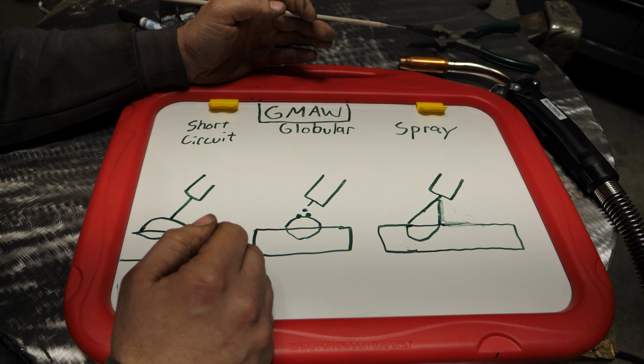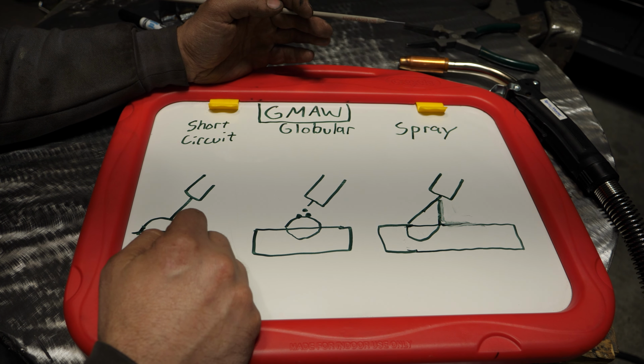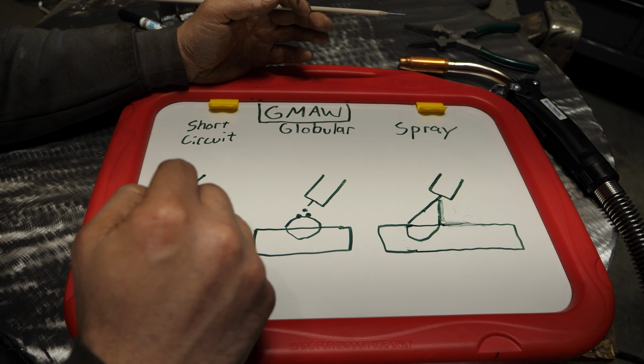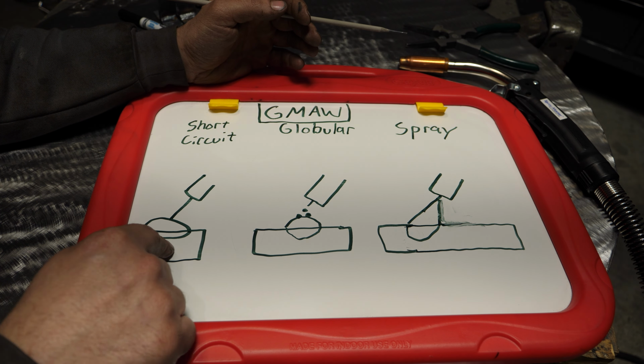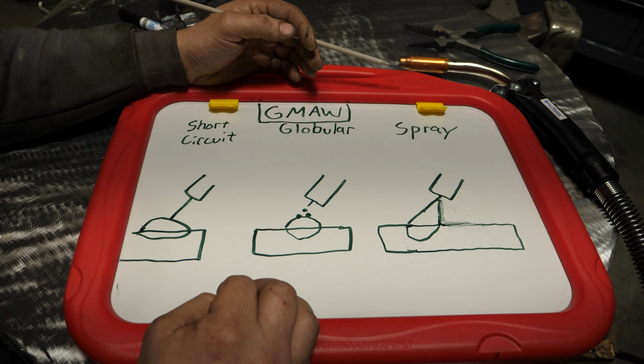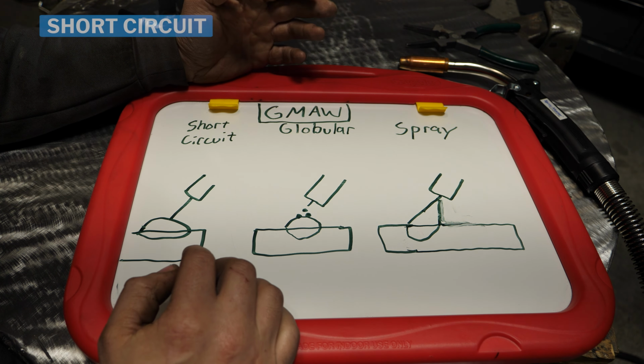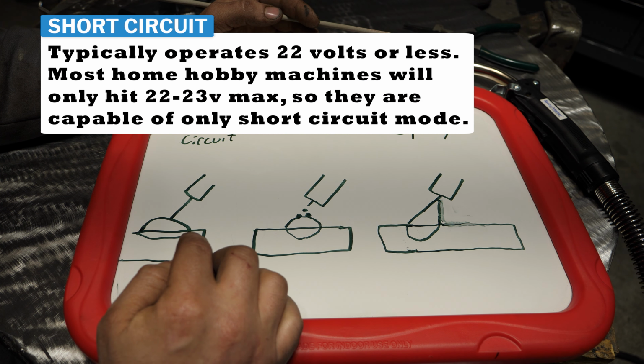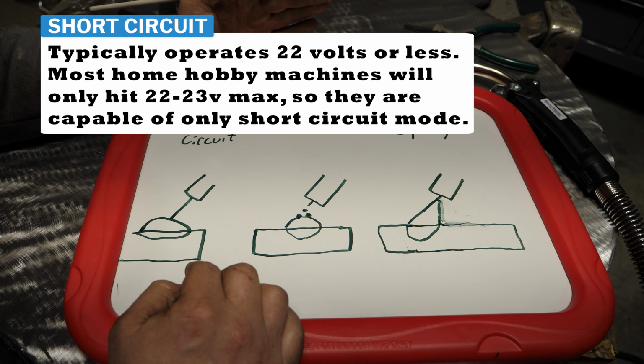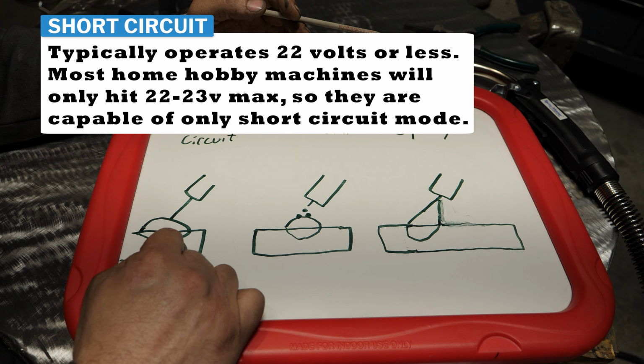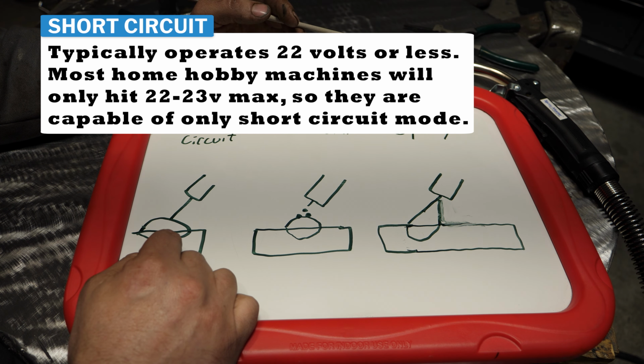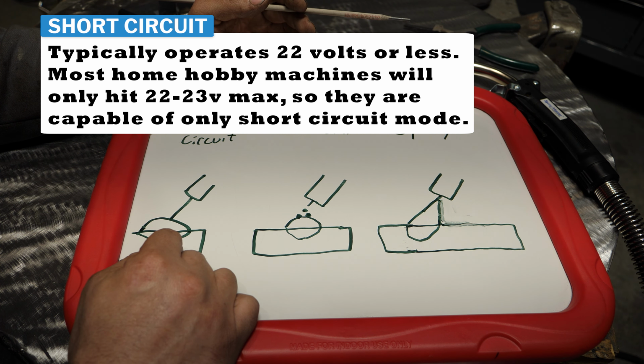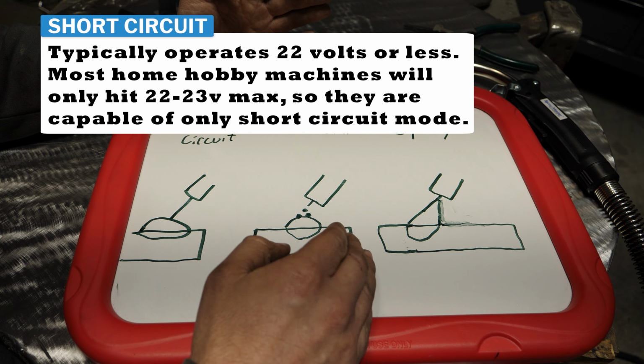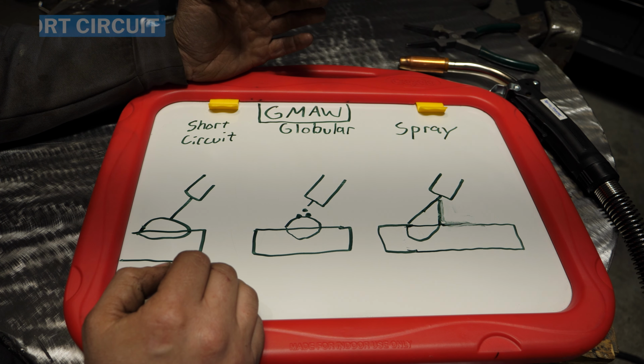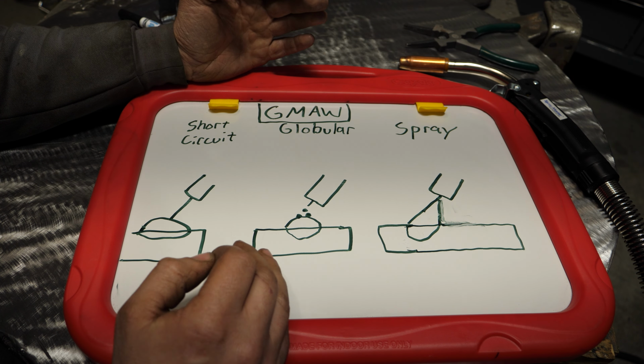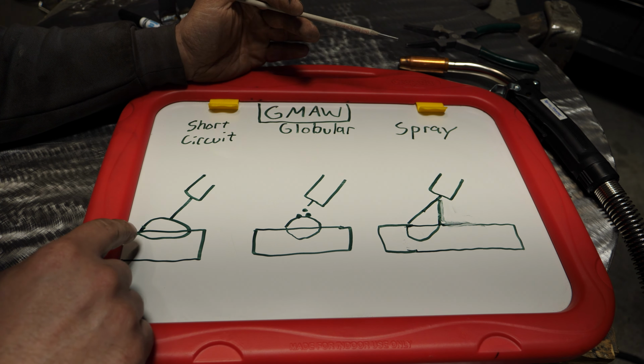So you're going to universally hear me call short circuit wire welding short circuit, short arc, or MIG, just flat out MIG. This is done on lower amp machines, so your 200 amp and under machines, with 100% CO2 shielding gas, or C25, which is 75% argon, 25% CO2. This process is the limit of what most home hobby wire welders are capable of doing. When you go to globular or spray, you can have issues achieving the set points required for them on a home hobby machine. And I'll explain why in a second.